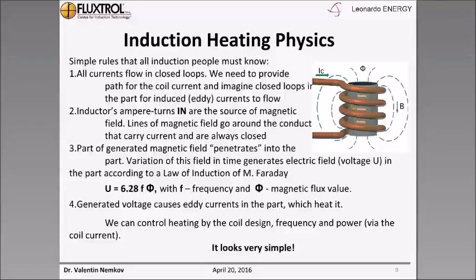We call it magnetic flux control. Part of the generated magnetic field in the work area penetrates into the part. Variation of this field in time generates an electric field or voltage in the part according to the law of induction of Michael Faraday. That's why the method is called induction heating. The induced voltage equals 2 pi f phi, where f is frequency and phi is magnetic flux value. The generated voltage causes eddy current flow in the part that heats it due to the resistance of the material. We can control heating by the coil design, frequency, and power via the coil current.